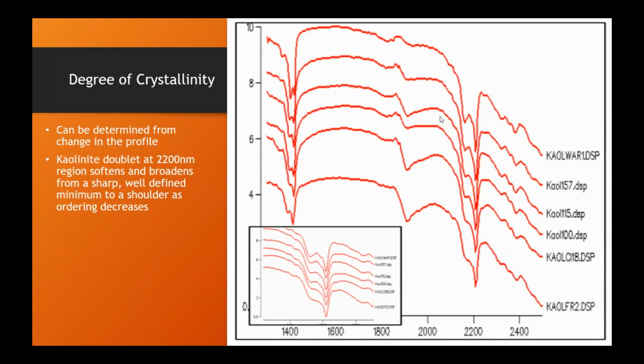The degree of crystallinity can be determined from change in profile using a calibration data set for comparison. So note how the 2200 nanometer doublet in this kaolinite region softens and broadens from a very sharp, well-defined minimum to a shoulder as ordering decreases. So this change in profile can actually be mathematically defined and utilized as a scalar. It is a function of random and sporadic filling of metal sites in the octahedral layer of the mineral. Empty and random sites decrease order and sharpness of the profile.